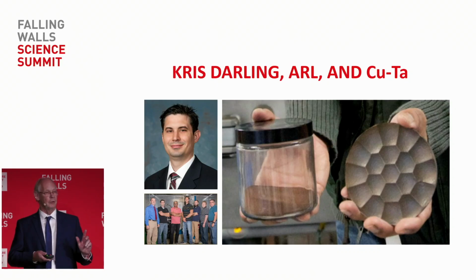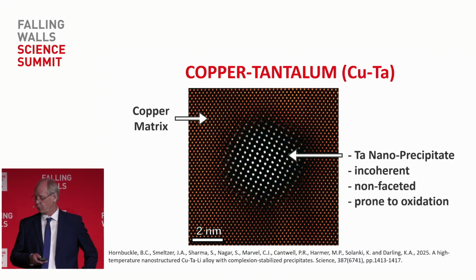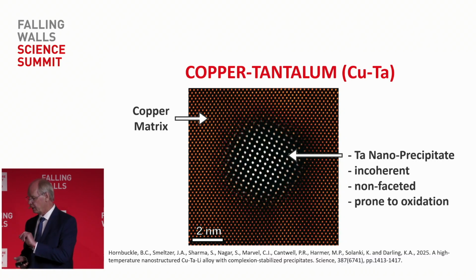So we've done this in a very special processing way to make this material. We've alloyed it with tantalum, which is insoluble in copper, and we've milled it at very high energy at cryogenic temperatures to dissolve mechanically the tantalum into the copper, then annealed it, heat treated it, and it precipitates out a nanocrystalline structure